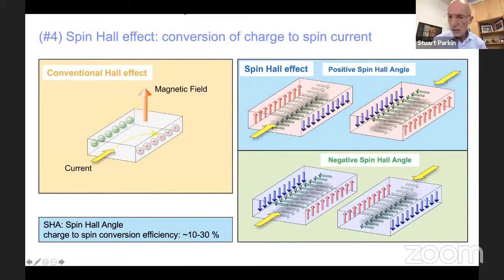And so a very important number is the conversion efficiency of the charge current to the spin current. And typically this was thought to be extremely small until a few years ago. In fact, the spin Hall effect was only observed 15 years ago by David Awschalom's group in a semiconducting material. And they observed it was a tiny fraction of a percent. And it was believed to be very tiny in metals until quite recently.